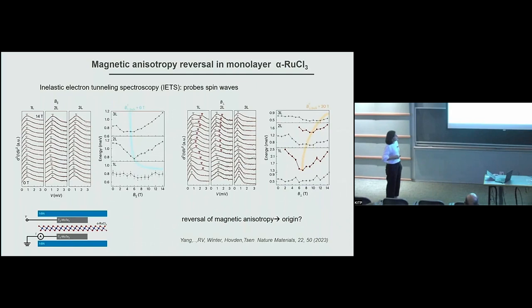Now he puts the magnetic field perpendicular to the monolayer. In the 3-layer system, what he sees is basically what you expect, because you have this in-plane anisotropy: there is no change in this lower magnetic excitation. In the 2-layer, he starts to see some change, but the magnetic excitations seem to be still the ones from the ordered state. However, in the 1-layer, with the magnetic field perpendicular, he's observing the same as you observed for the bulk with the magnetic field applied parallel. So basically, it is as if in the 1-layer you would have a reversal of the magnetic anisotropy.